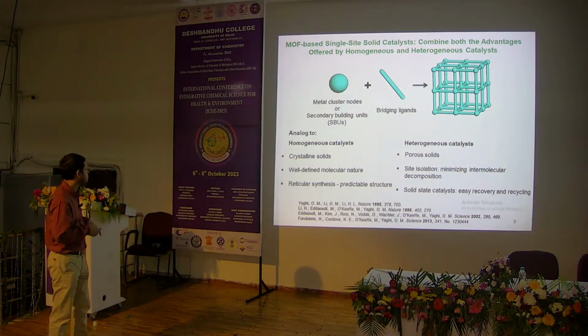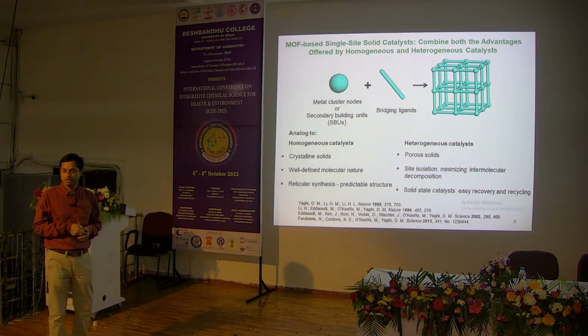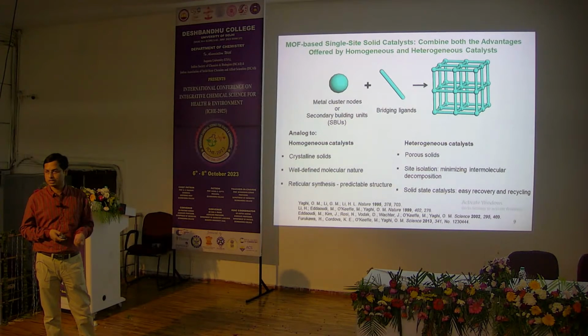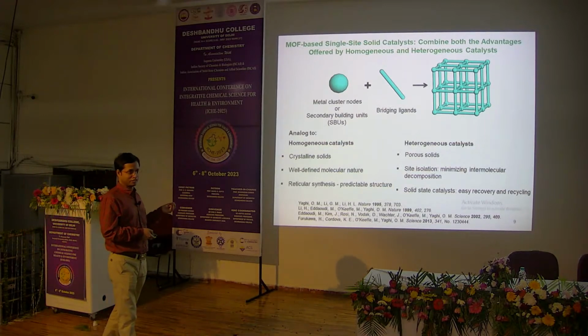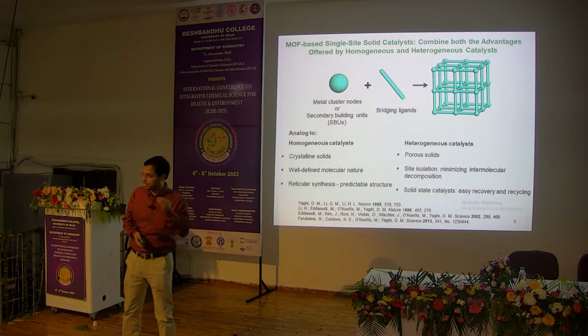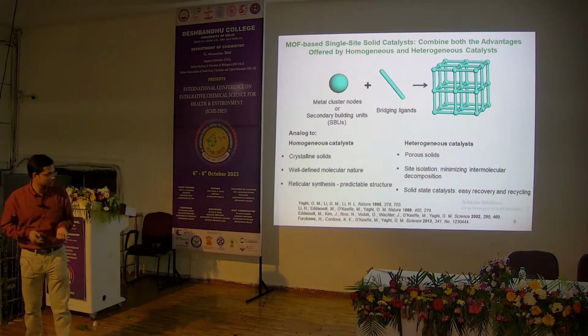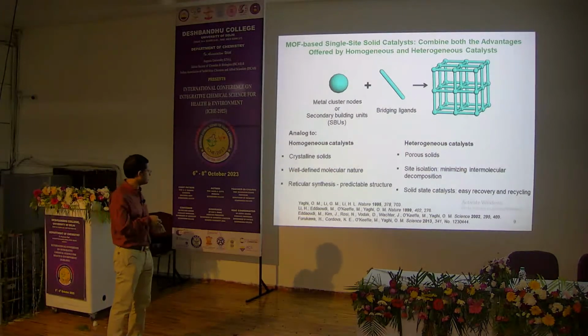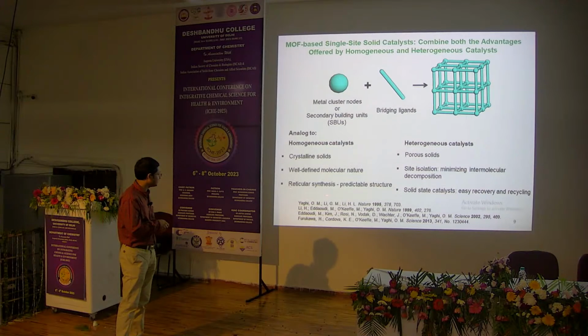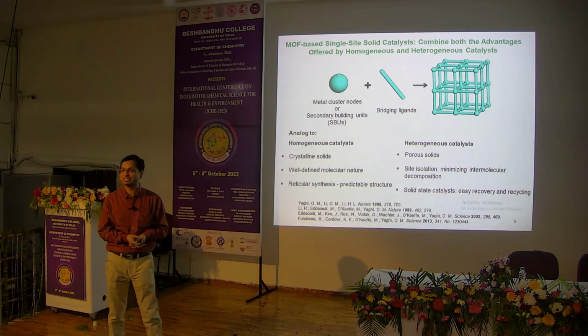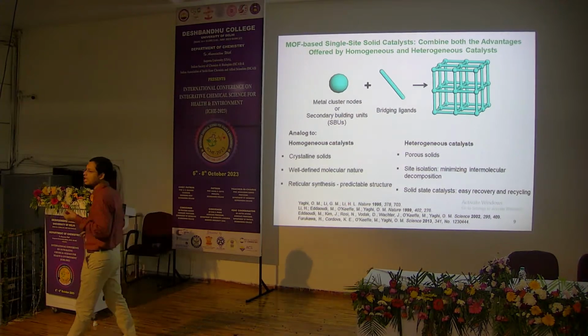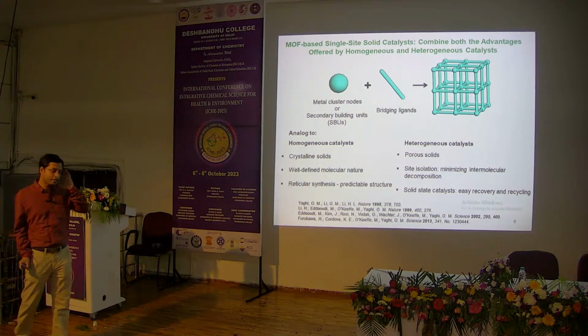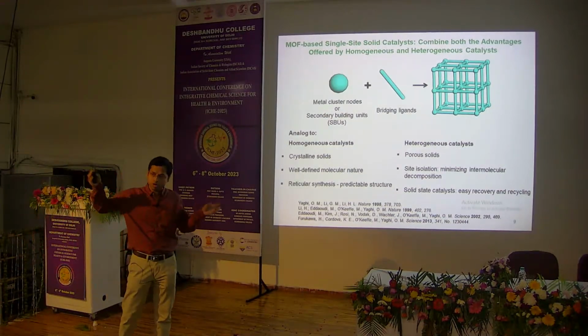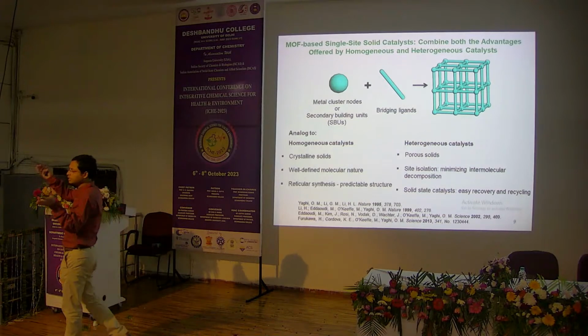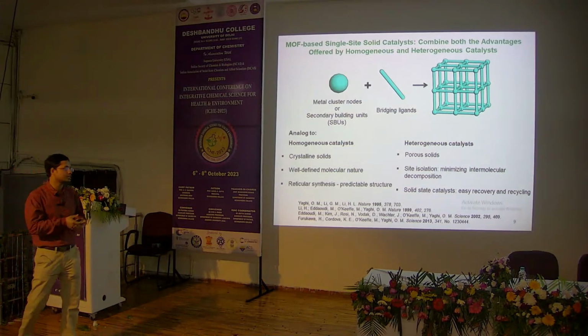First of all, this is a crystalline material. You can get the structure by single crystal XRD. If you do not get the single crystal structure, then you can deduce the structure from the powder XRD. It has a well-defined molecular nature, and not only that, it has a reticular synthesis. Most of the MOFs are isoreticular. That means you can tune the pore sizes. For porous materials, you can decrease or increase the pore sizes, keeping the structure the same.